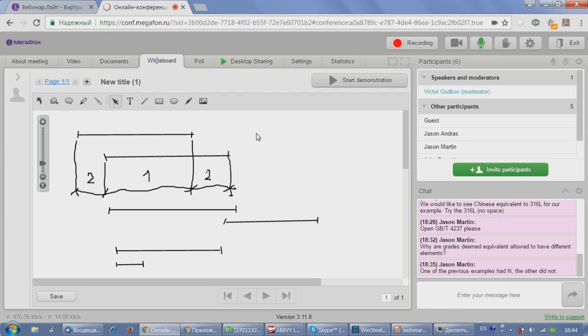So the main idea of search is that contents are the same if there is some intersection of these branches. But we can have different cases. For example, we can have such cases when this intersection is not very good. If you don't have a lot of grades, maybe it is possible. But if you have 100 grades and wish to find the closest composition, it is better to exclude grades with such a small intersection. And to do this efficiently, this is marked with number 1.